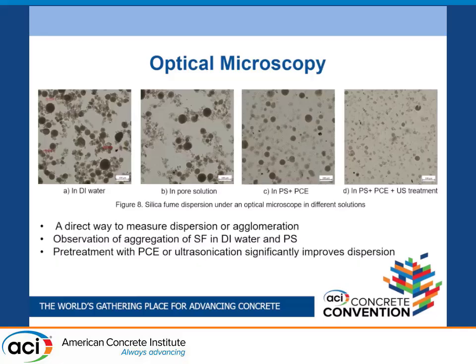These 4 figures show the representation of silica fume in different conditions. The first was in DI water, where we see large flocculates of the sample ranging from tens of microns to several tens of microns. In pore solution the condition is the same, so we see larger flocculated samples.